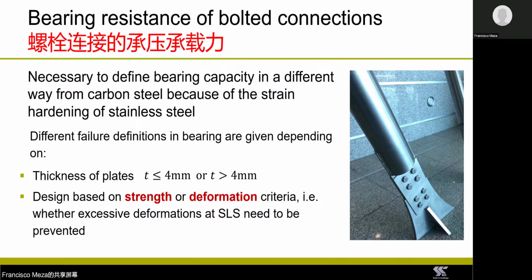With regard to the bearing resistance of stainless steel bolted connections, there are some differences with respect to the equations that are used for carbon steel. And this is because the equations that are used for stainless steel take into account the more nonlinear stress-strain characteristic of stainless steel, and also the more significant amount of strain hardening. So the rules for calculating the bearing resistance of stainless steel bolted connections distinguish between plates with thicknesses of up to 4 millimeters and plates with thicknesses greater than 4 millimeters. And this distinction is made to align with the rules that are given for carbon steel bolted connections.